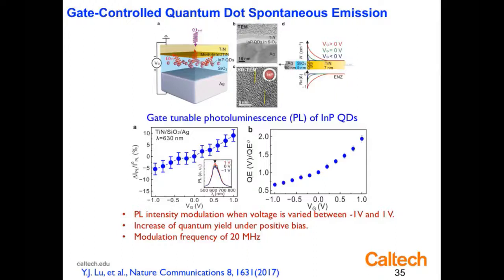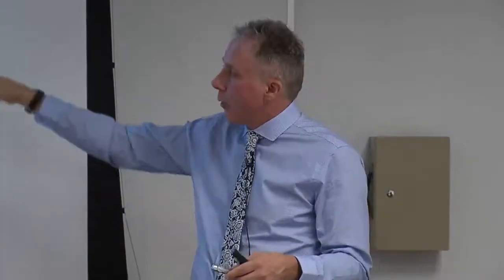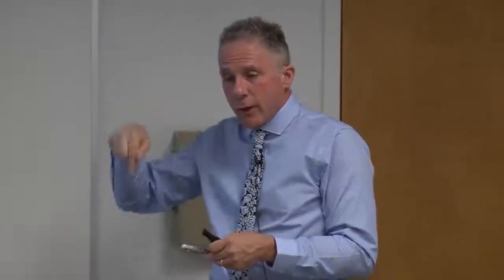So we actually have proposed this, and Samsung is interested in this as a potential future display technology where you optically pump the quantum dots and then simply change the amount of light coming out of each pixel by tuning its local density of optical states. The advantage of that is you don't have to inject carriers into the quantum dot. That has a significant reliability impact on the quantum dot displays that involve direct carrier injection. So it could be a very reliable display.